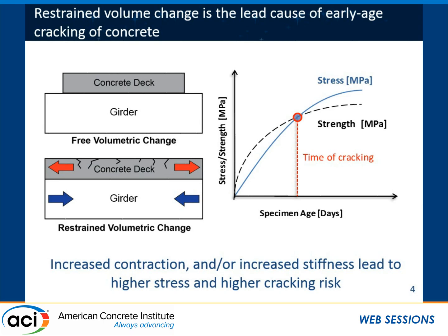But just looking at this very simplified version of the event, we can see that increased contraction, increased shrinkage, and increased stiffness of the concrete would lead to higher stress and higher cracking. Increased contraction could be, for example, when a concrete has a higher paste content, that would shrink more. Or if it has a higher cement content and a higher heat of hydration, the thermal contraction will be more. So increased contraction, as well as increased stiffness, or the elastic modulus, or inverse of compliance of concrete, would impact the amount of stress that generates in concrete. So the concretes that are stiffer, that are higher strength, somewhat counterintuitive, would be more prone to cracking.